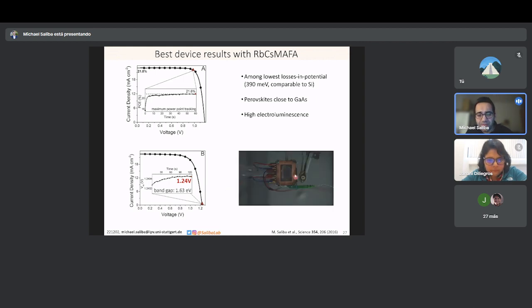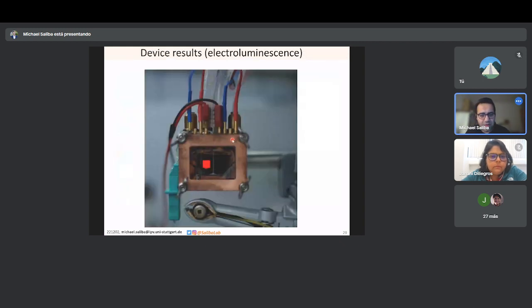This is also the stability holder. And already at ambient light conditions, the solar cell is very beautiful, showing LED behavior. And this is not even optimized yet. The layers are still too thick, there's a lot of self-absorption, and the contacts are not optimized for LEDs either. But still, it shows very clearly this is an extremely efficient semiconductor with very little non-radiative recombination. Practically all the recombination is radiative in this case, the kind of stuff that you know from the Shockley-Queisser limit. Here you see a close-up. Very nice.